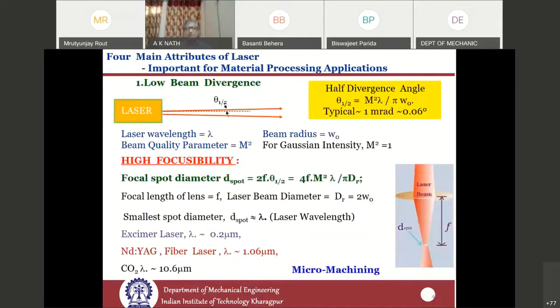Now, this is a basic slide which shows how the beam divergence affects the laser material processing. So if you see a laser whose beam radius is w0, and wavelength is lambda, and the beam quality factor is M squared, and this M squared value for a Gaussian beam is 1, then in that case, the half divergence angle is given by M squared lambda by pi w0. What is the significance of this? The significance of this is that when we have got such a laser beam and we try to focus with the help of a lens of focal length f, then the spot diameter we generate is given by 2f into half beam divergence, where f is the focal length of the lens.